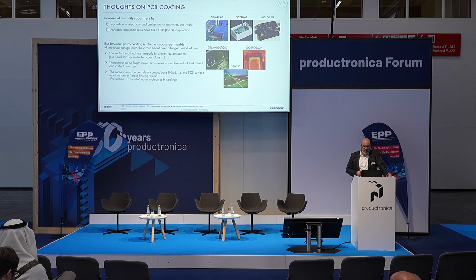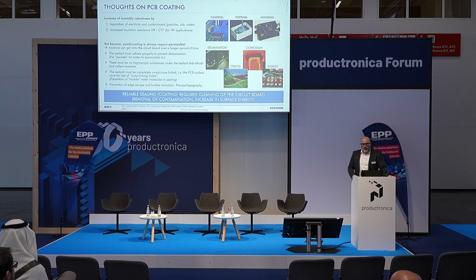Of course, you also need to prevent any cracks or issues of the coating itself. So cross-linking needs to be optimized. And there are several risks for that. One is process-related, like the drying process, but the other one is also related to contamination on the surface, which can prevent proper cross-linking of polymers during the drying process. And then, of course, again, the process needs to be stable so you don't have any bubbles, but that is a real process optimization topic. So again, to have a really reliable coating, you need to make sure that the surface is well prepared, and this is done by cleaning.